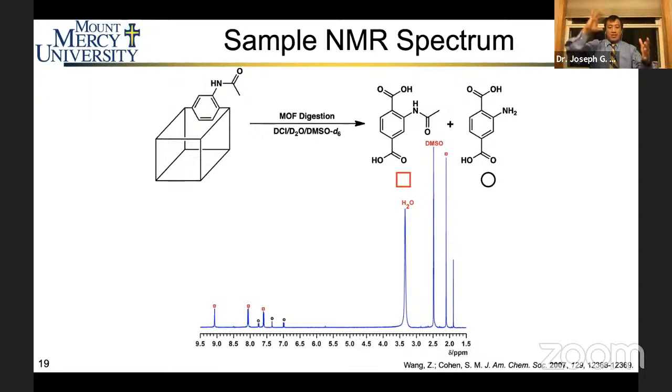And so the outside functional groups react faster than the ones on the inside. And so we tend to not get 100% reaction, but we can get as high as 98 or 99% conversion, which is many times all you necessarily need. And you're going to see here in a little bit that some of those conversions aren't even that high.